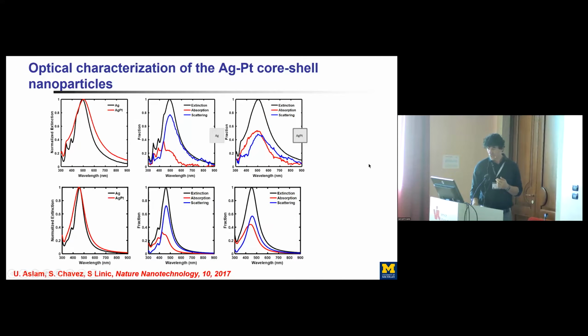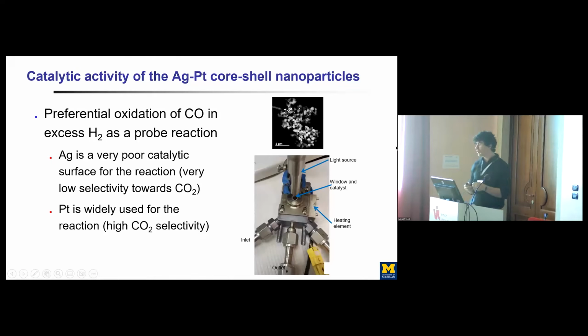Since I'm short on time, I'm going to go quickly. So then we ask a question: if we can do this, we should be able to drive plasmonic chemistry on this platinum, expanding the portfolio of materials that we can use. So we used exactly this material to perform a preferential CO oxidation in the presence of hydrogen. It's a very important commercial reaction. And we know that silver is a very poor catalyst for this process, it actually cannot do it. On the other hand, platinum is widely used for this process. So the question is, can we now drive this reaction with this platinum-silver core shell nanoparticle, because it can happen only on